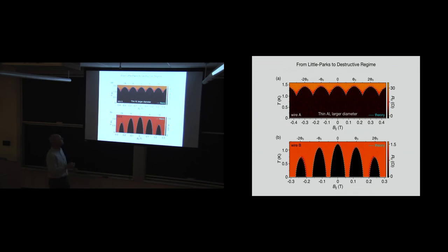By the way, if you make the diameter bigger, it doesn't need to be destructive. You could just have something which goes by the name of the little Parks effect, which is the modulation of the critical temperature as a function of the applied magnetic field. But the little Parks effect is allowed to go all the way to zero, which it does in the so-called destructive regime. But the theory knows about it, it's a different thickness or a different diameter, or whatever it is, and it just plots up just the same. The shell is cool, but boring in a sense, that it's described perfectly by the expected physics of mean field theory.